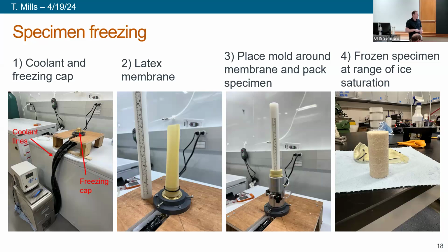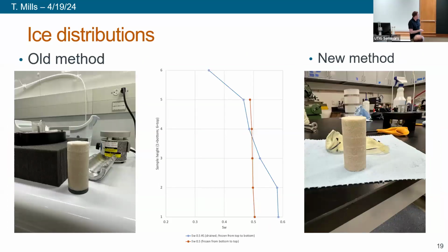But what we'll do is we'll pack one layer and let it freeze, and then we'll pack the second layer and let it freeze. And when we do that, we can end up with a sample with homogeneous ice distribution. And so just as an example of the before and after, over here on the left, we have a sample that's created from our old method where we just built the whole sample and then tried to freeze it, and our new method over to the right.